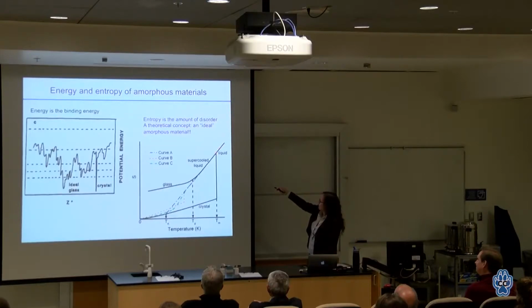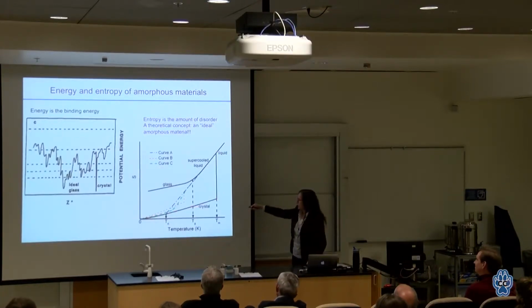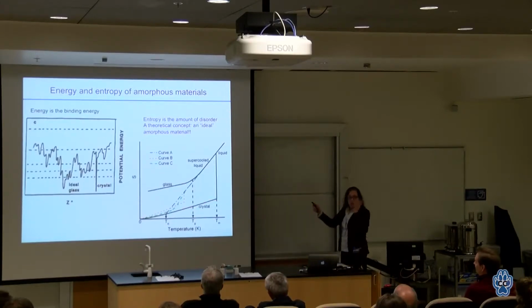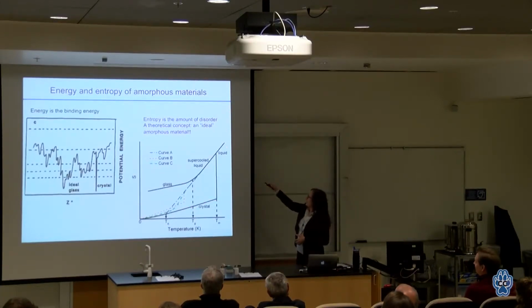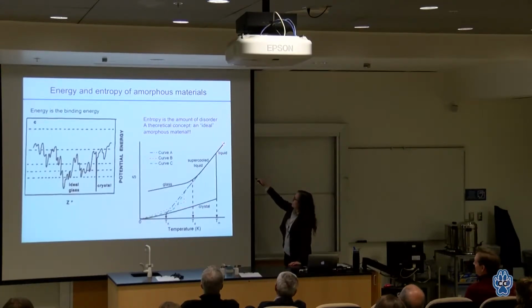Looks like that. When I hit the melting or freezing temperature, in equilibrium, this should drop down to the crystal. So it's a first order phase transition, liquid to frozen. Discontinuity in the entropy, and then I have the entropy of the crystal, which goes to zero at T equals zero. So that would be the equilibrium thing where I have liquid, crystal, and then T equals zero. In a liquid that I supercool, what happens is I don't crystallize.